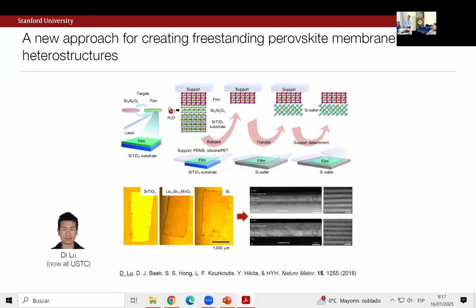So D is the guy that really had these very creative ideas and developed them. And so simply speaking, the system is like this. We happen to be using pulsed laser deposition in our nice dry chamber. This is basically another layer to grow in some heterostructure. And the point is, starting from a substrate, if we grow this soluble buffer layer and then subsequently grow a film or heterostructure, we can then dissolve this layer off and transfer it onto whatever other substrate you'd like.